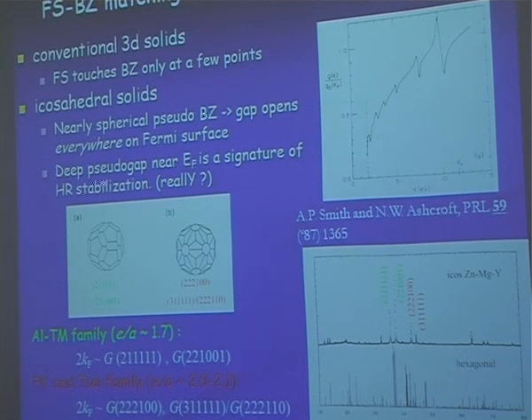But the interesting thing is that different values of the E over A ratio are estimated for the aluminum transition metal family and the Frank-Kasper and the Tsai family. For the aluminum transition metal family, E over A is estimated as 1.7, as already mentioned by An-Pang Tsai yesterday. In that case, the Fermi sphere touches a little bit smaller Brillouin zone, shown here. For the Frank-Kasper and the Tsai family, E over A is around 2, so the Fermi sphere is a little bit larger. Then the Fermi sphere touches a little bit larger Brillouin zone. So it seems very reasonable to have this for the different families of quasicrystals.